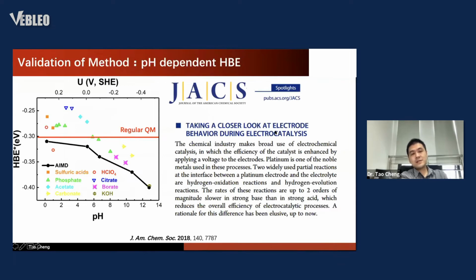So the question people ask us is how accurate your simulation is. Here we provide evidence. There is one well-known experimental result that the hydrogen binding energy has a pH dependence. The points shown in this figure are the experimental results. We can clearly see the trend that the hydrogen binding energy changes with the pH. Basically, when you have higher pH, the hydrogen binding energy is actually stronger. If you use regular QM methods, you cannot capture this. What you end up with is just a constant binding energy.